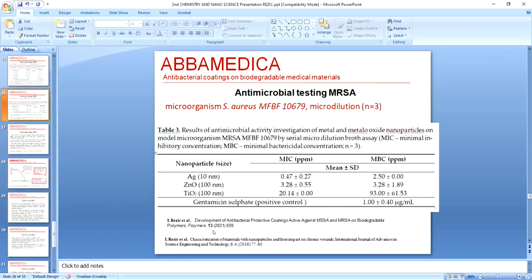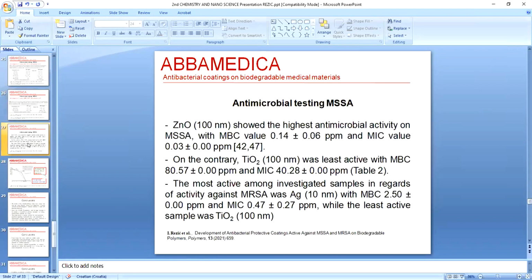So, what does this mean? That means that if we use some other microorganism, another method, we can see positive effect with different elements. And when we compare the results, what has been shown? So, zinc oxide of 100 nanoparticles show the highest antimicrobial activity on MSSA.